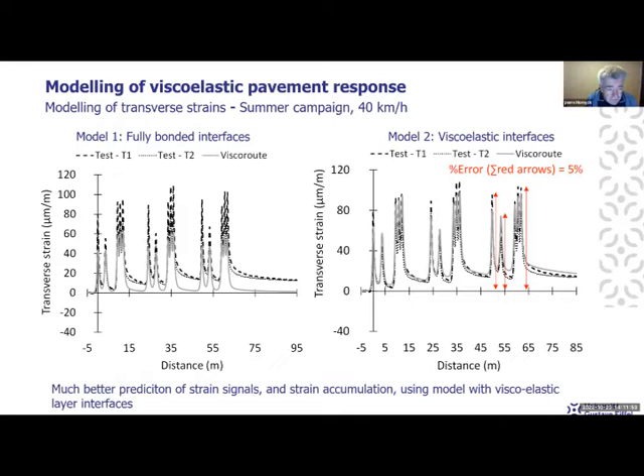And first, logically, we tried to model the response with viscoelastic asphalt layers, but with fully bonded interfaces. And we found that with fully bonded interfaces, we couldn't reproduce well the strain signals. The asphalt material properties were determined from complex modulus tests in the laboratory. But with the bonded interfaces, you can see the modeling is in gray. The strains were lower than the measured ones.